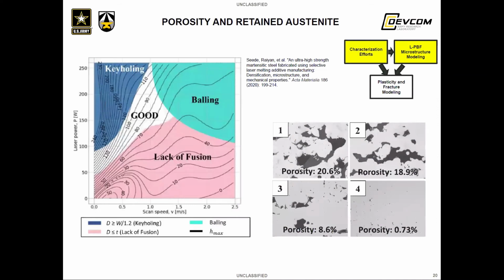On the next slide, this depicts a study performed at Texas A&M on the formation of porosity in AF9628. For those familiar with laser powder bed fusion, the various modes of forming porosity will be very familiar already. Keyholing porosity is when the laser power is high and the speed is low, so that regions of material absorb too much energy from the laser and essentially vaporize, and that leaves behind pores. If the laser is too weak, or if it's moving too quickly, not enough energy will be deposited into the material and it will not fully melt or will only partially sinter. Balling is another melt pool phenomenon that occurs from a combination of high laser power and speed. Each of these are normally purposefully avoided due to the detrimental effects that porosity has on final part performance.